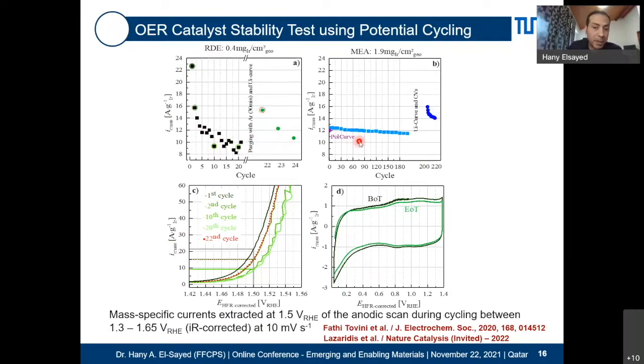And the interesting part, again, as I guess now you expect this, is for the MEA, you do the potential cycling, it's more or less not really changing. And you do the regeneration, it starts from an even higher value. And then it will go basically down in the same pathway, not really losing anything.